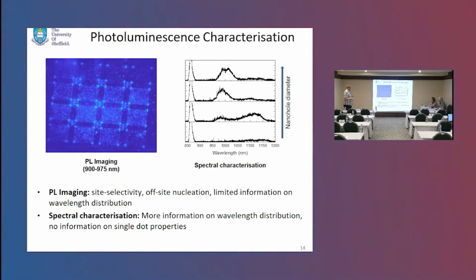But you can then start to see luminescence from the sites, and you can start to see relative intensities. You are towards the end of the range of the camera if you're going out to 975, so things may start to seem darker than they actually are because it's a silicon detector. So this is kind of what we'd see from the first technique. We're seeing some kind of ensemble. For the second technique, we kind of see whether we're getting good occupancy and so on. So we get information on the wavelength distribution from this method and site selectivity here.